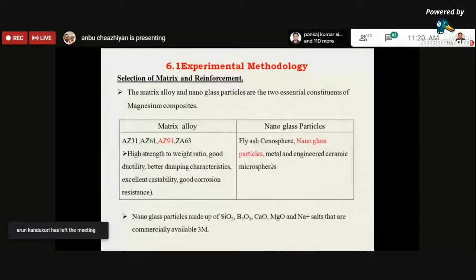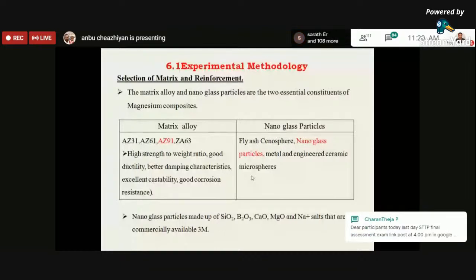AZ91 as a matrix material has a high strength to weight ratio, good ductility, better damping capacity, excellent castability, and good corrosion resistance. Based upon these factors, we have chosen AZ91 as the matrix material. We have also chosen nanoglass particles as the reinforcement. They are essentially nano hollow particles. Some researchers use these hollow spheres for developing metal foams. The composition of the nanoglass particles is SiO2, B2O3, calcium oxide, magnesium oxide, and sodium salts.